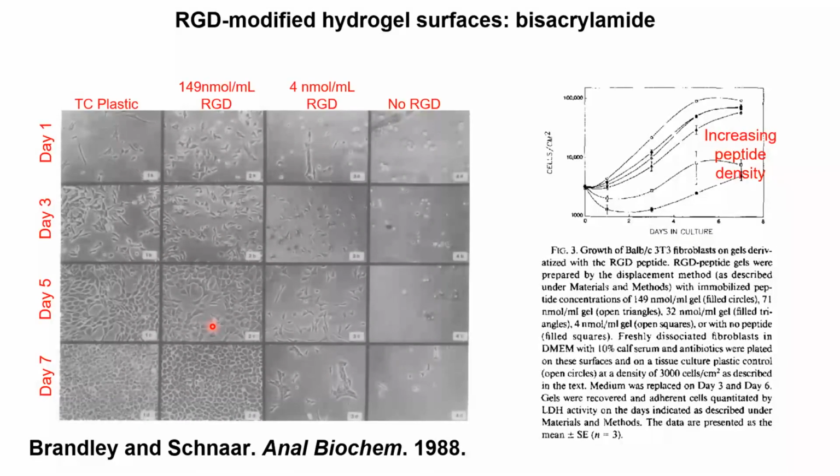And one thing that's important here is that this is done in the presence of serum. So on the plastic, even though there's no RGD added, proteins from the serum like vitronectin can stick down and be presented. The ECM proteins that the cells make over time can also change their adhesion and proliferation rate. But with this biomaterial that inhibits protein adsorption, we really have far better control over non-specific adhesion. So we know that the only thing the cells are really sticking to in this system is this RGD tripeptide.